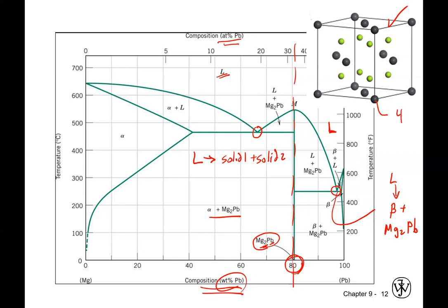And it looks like the magnesiums are sitting in these tetrahedral sites, and so these are fully in the cell. So there's 4 on top, 4 on bottom, right? Because there's tetrahedral sites right behind every single corner. So that's 8. Okay, so we said there's 4 lead in the unit cell, 8 magnesiums. And so you can see that's a 2-to-1 ratio, like the stoichiometry says.